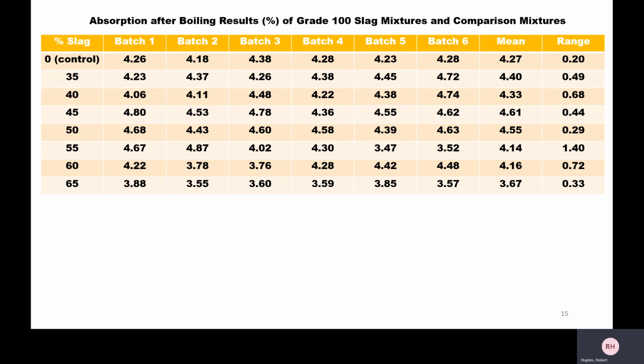Porosity, other studies can say that the use of SCMs doesn't necessarily decrease porosity, but it will decrease permeability. So at a very high substitution, we did see a decrease in porosity, a decrease in absorption after boiling, which is good, but again, not the exact results we're looking for. So it is good to see that it is acting as it should, but at extremely high substitutions.